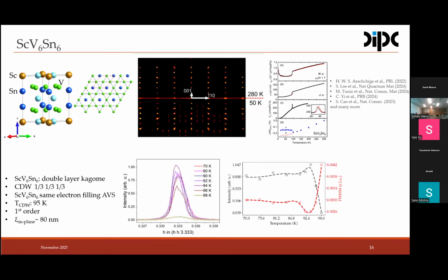We first start with ScV6Sn6. It contains two Kagome layers made of vanadium and trigonal germaniums. Sorry, trigonal tins. The blue atoms are trigonal tin. The green are vanadium. The blue trigonal tin are not aligned in the Kagome layer. Actually, they are slightly above and below the Kagome plane. This is a consequence of the small size of the scandium atom, which is located at the same height as the honeycomb tin layer.